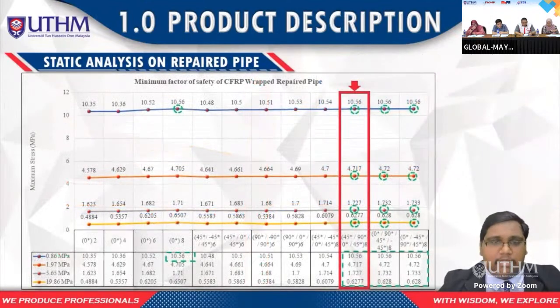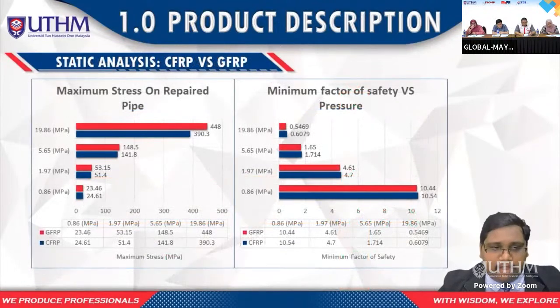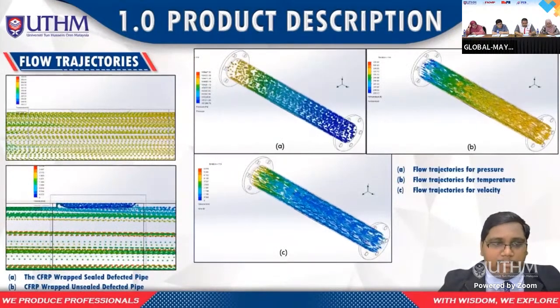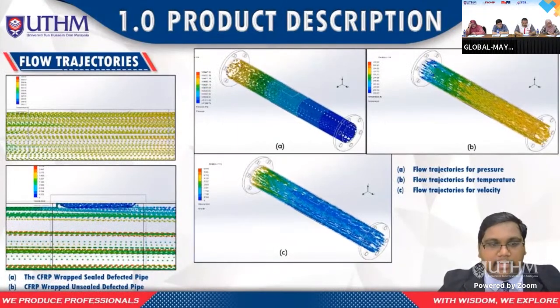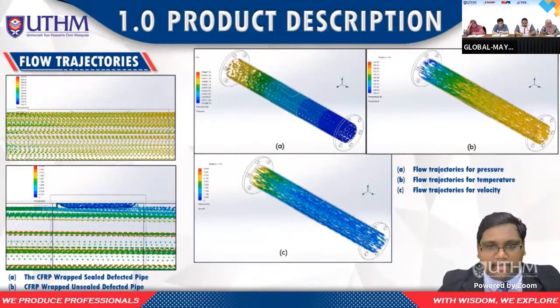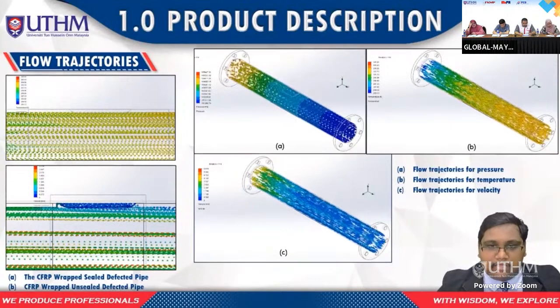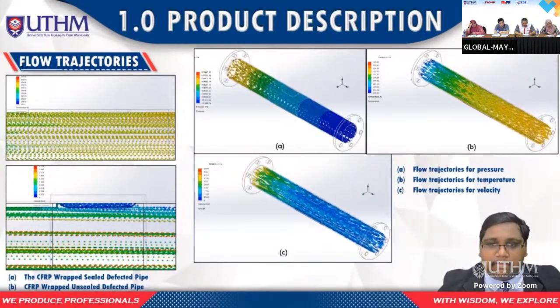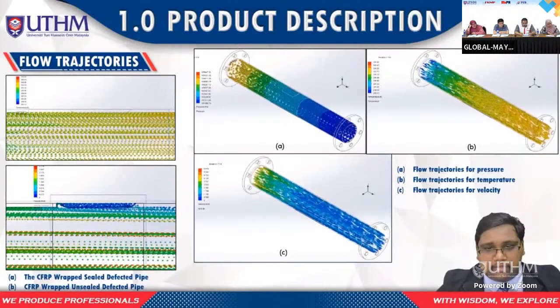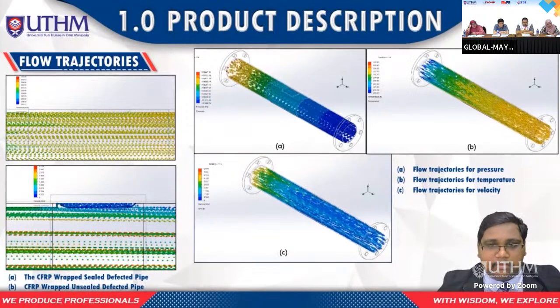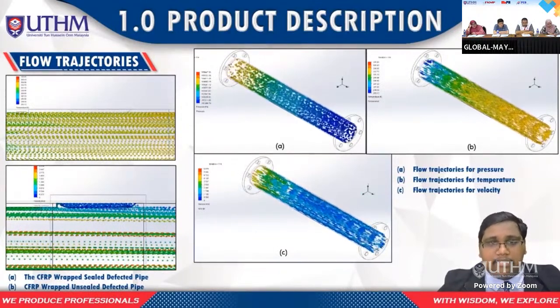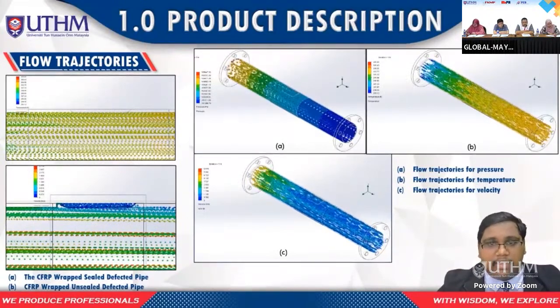And interestingly, the same orientation seems to have a higher minimum factor of safety for carbon fiber reinforced polymer as well. And for the comparative study approach, we found that the carbon fiber reinforced polymer possesses better properties compared to glass fiber reinforced polymer. And after the pipe structure has been wrapped, the CFD analysis has been done to make sure that the product flow is not affected after or before the pipe wrapping material has been applied. In SolidWorks, whenever there are no openings in the watertight system, then the wrapping structure is successful and effective against any leakage.